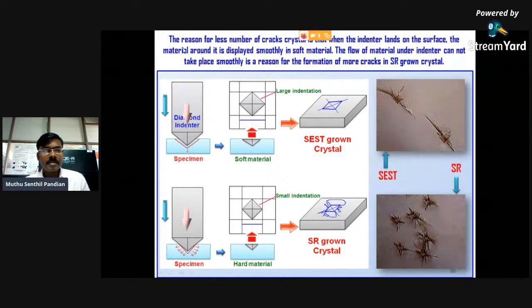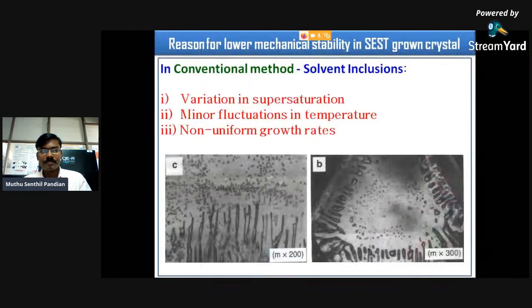So this is the animation. The reason for less number of cracks. This is the SEST crystal. The reason for fewer cracks in the conventional grown crystal is that when the indenter lands on the surface of the crystal, the material around it is displaced smoothly in the soft material. In the SR crystal, the flow of material under the indenter cannot take place smoothly. This is a reason for formation of more micro cracks in the SR method grown crystal. This is almost common for all the SR method grown bulk size single crystals.